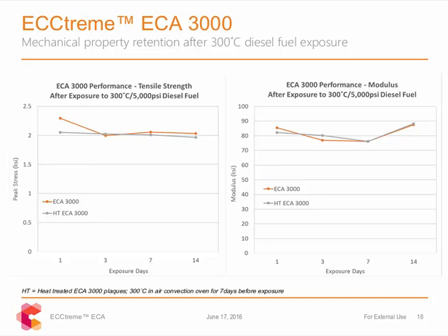and pressures. Like shown here is exposure to diesel fuel at 300 degrees Celsius and 5,000 psi for 2 weeks. Like all fluoropolymers, of course, ECA does show some limitations at certain temperatures and pressures in different exposure systems. But overall, we have observed a retention of physical properties in ECA that's unlike any other melt-processable fluoroplastic performing at these temperatures. So again, here you can see that in high-temperature, high-pressure exposure to diesel fuel, both ECA and ECA that has been exposed to extreme heat show little to no effect on tensile strength or modulus over the span of 2 weeks at pretty extreme conditions.